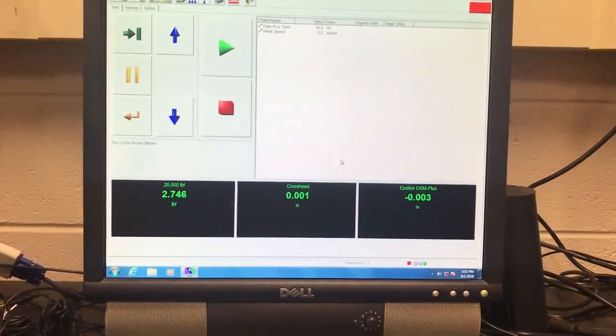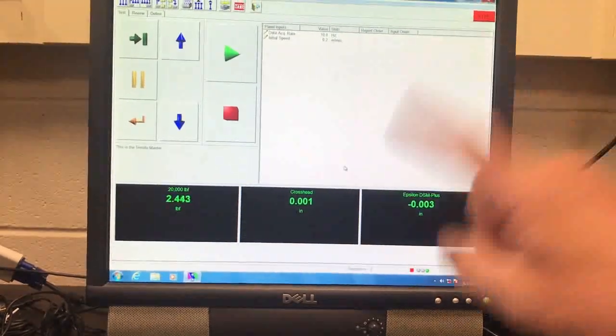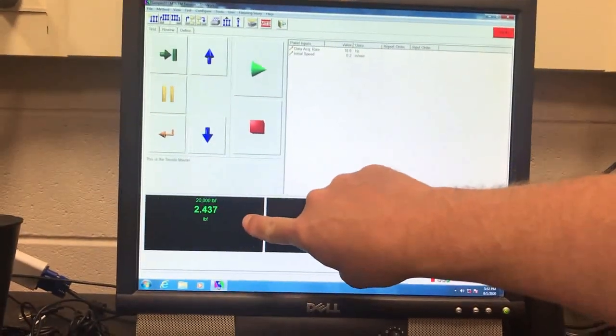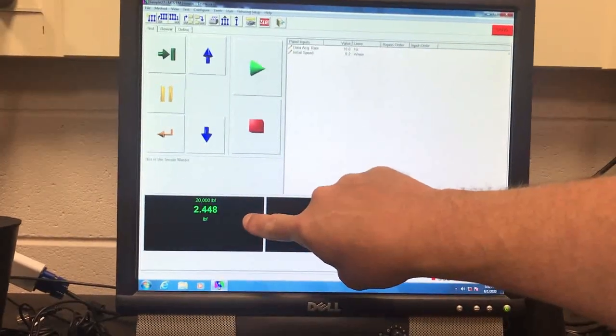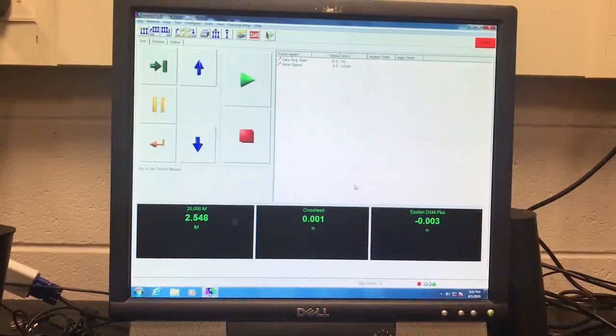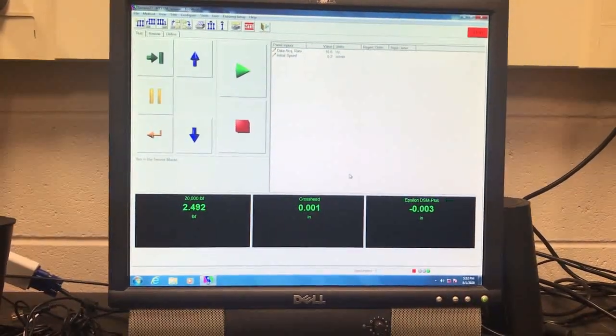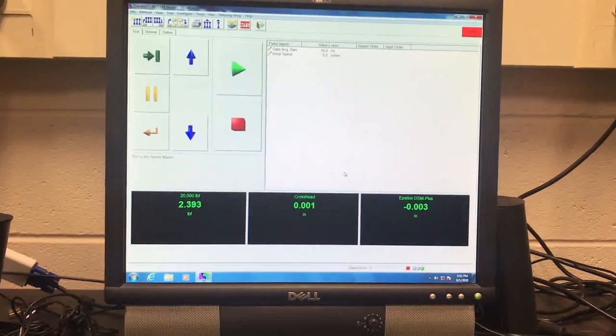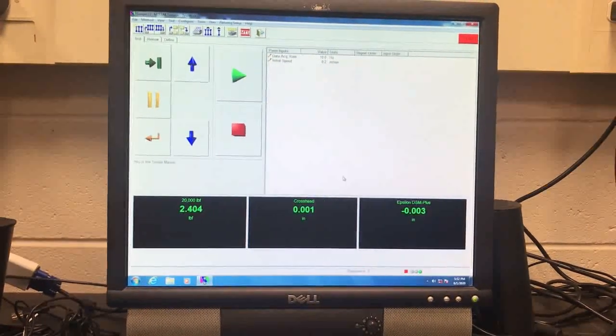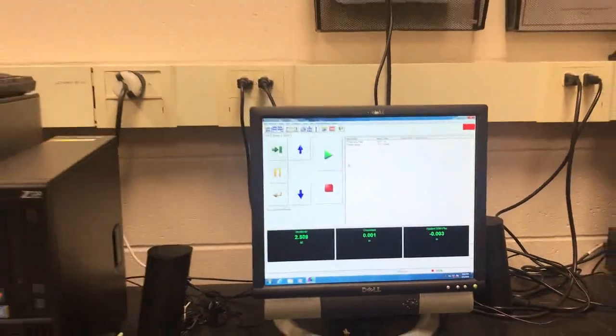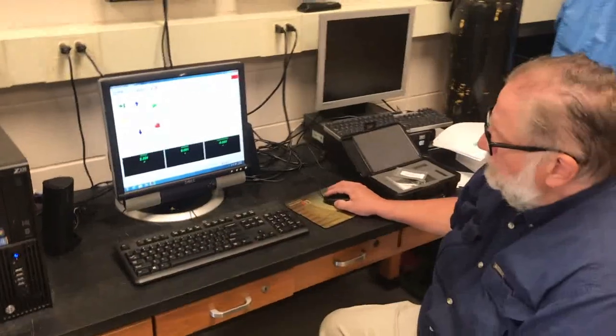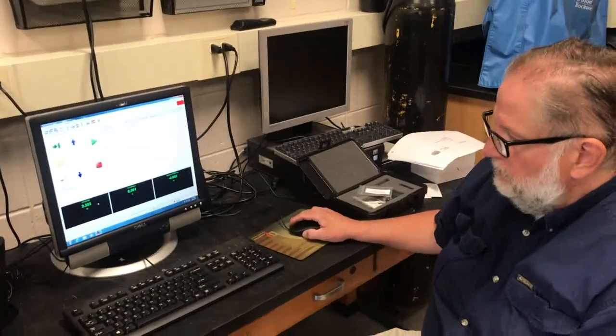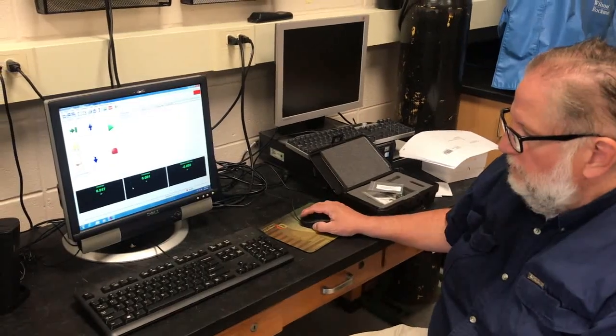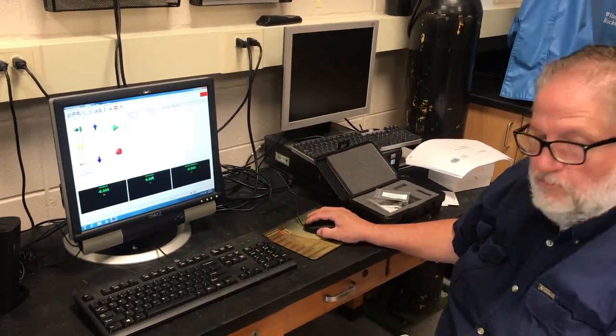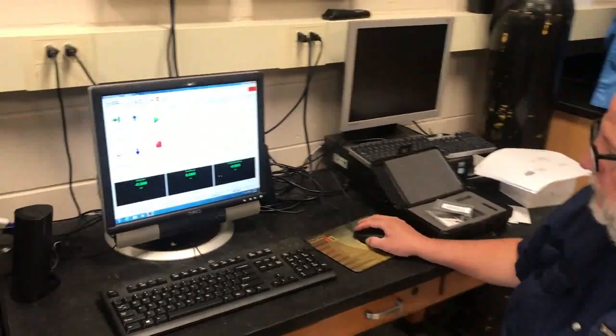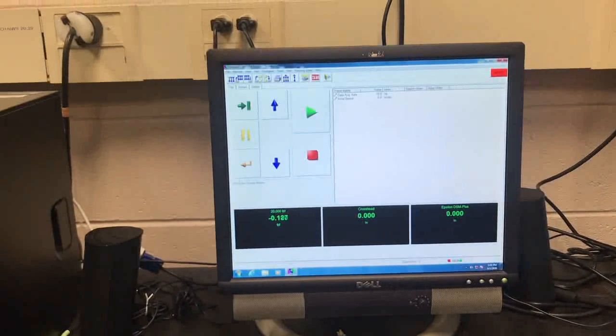If I were to move the crosshead up and I got no response here of force, that would tell me that I had too much slack in the assembly. But the fact that I have a positive number tells me that we have eliminated the play in the rig, and we're 1 step closer to the test. Okay? Now, finally, the next thing you want to do is go ahead and 0 all the channels. Right click, 0 the force, right click, 0 the crosshead, which is just an indication of the crosshead movement. And you can go ahead and 0 the extensometer as well.